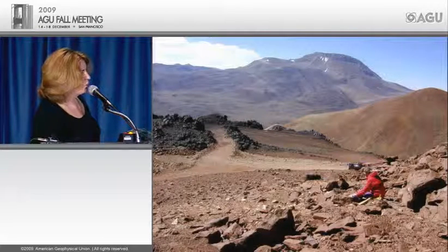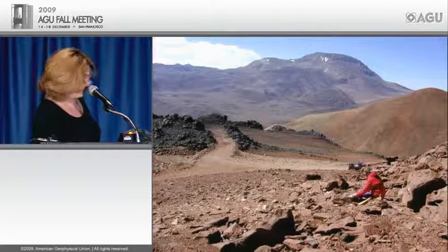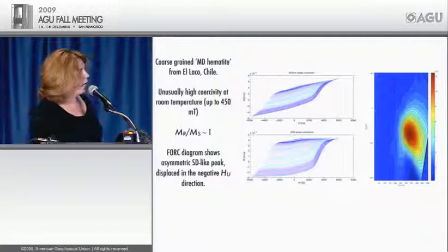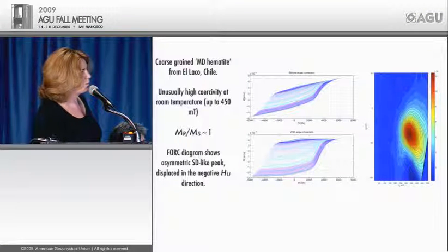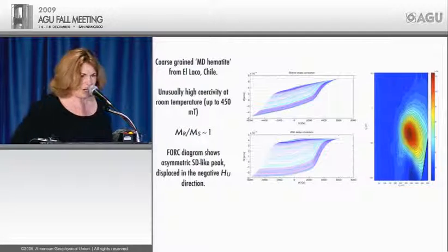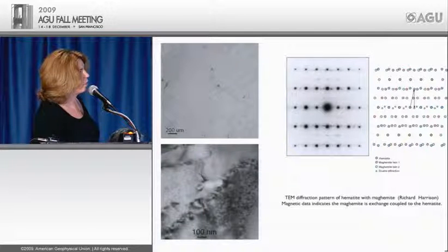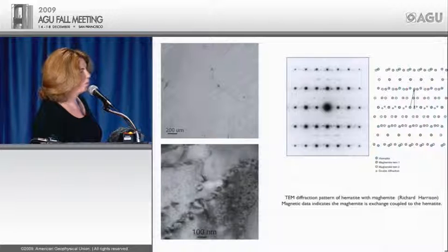The last sample that I'm going to show you from this part is from the El Laco deposit in Chile. And this is a hematite-rich sample, which has very high coercivities, from what you can see from the hysteresis loops here. They're FORC loops, and you can see an extraordinary coercivity. And again, we had the question, what do we have? Because if we go in at the SEM scale or the microprobe, we're pretty much getting hematite. If we go to the TEM, we have two phases there. And again, we believe these phases are exchange coupled. And the second phase is a maghemite. And so this very fine intergrowth is what's probably carrying the magnetization there.